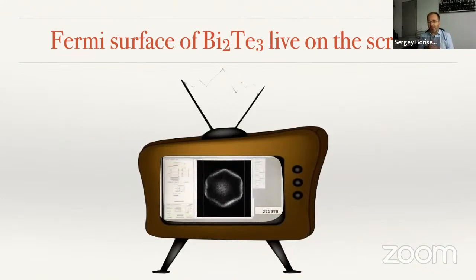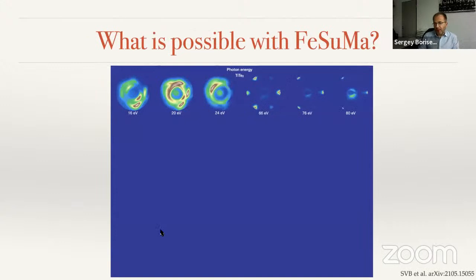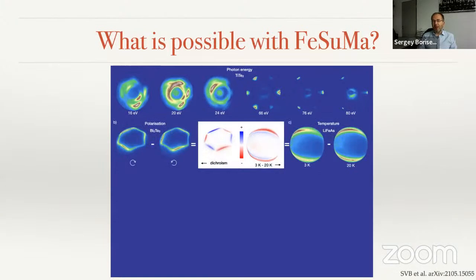We were very surprised that after a very fresh cleave, you see the Fermi surface immediately, seconds after the cleave, and we were surprised to see how the Fermi surface can change within a minute after the cleave. These opportunities, of course, expanded the possibilities of photoemission. Apart from different photon energies, and we tested the technology already at different synchrotrons, you could do very fast measurements of the dichroic signal.